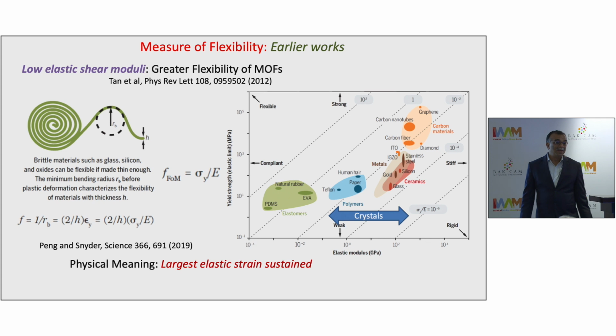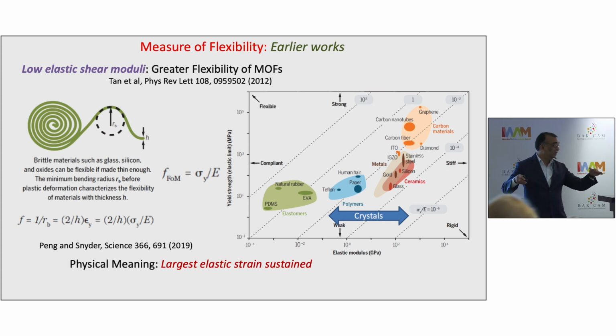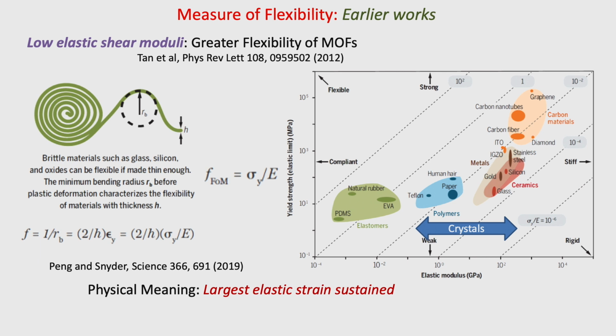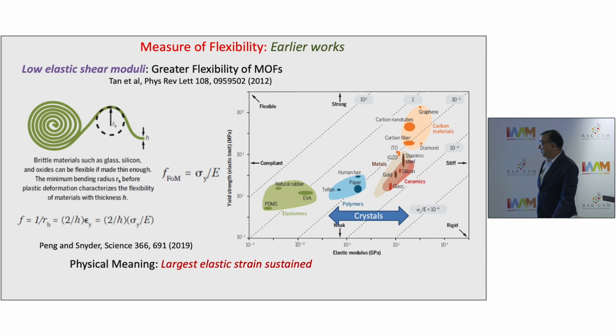On the left, you will see, although this is sort of from the engineering perspective, you take a sheet of a material and try to bend it, and the radius of curvature through which you can bend that sheet is decided by this simple formula, which involves a geometrical factor 2/h, h being the thickness of the film. And the second factor is intrinsic to the material which makes that film, which is sigma y upon E. So sigma y is the yield stress of a material, and E is the corresponding elastic modulus of that material.